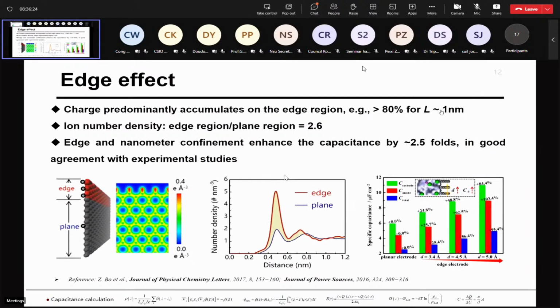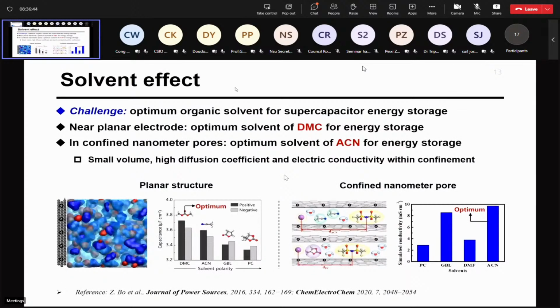Another important nanoscale effect is called the edge effect. We found that the charge predominantly accumulates on the edge region, and the edge can provide a unique high power and energy density at the edge area. In this work, we also studied the influence of the solvent on the energy storage performance. We found the optimum solvent for the electrolyte to deliver high power and high energy density supercapacitors.